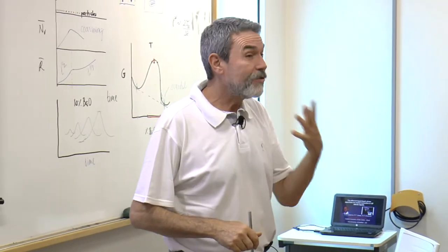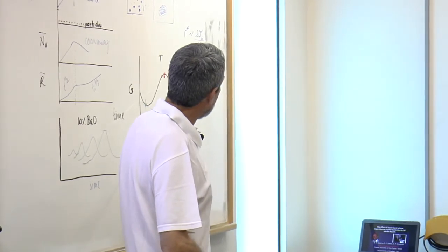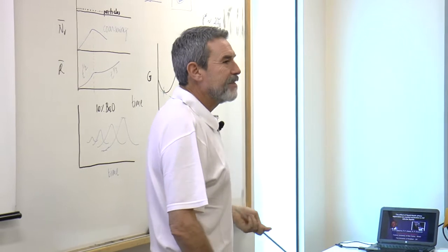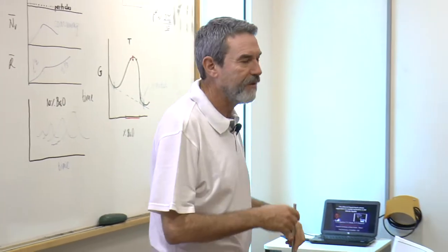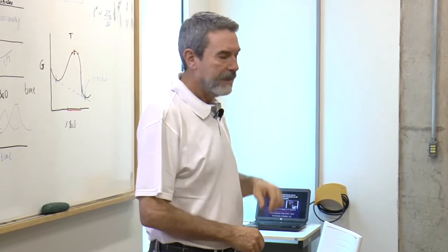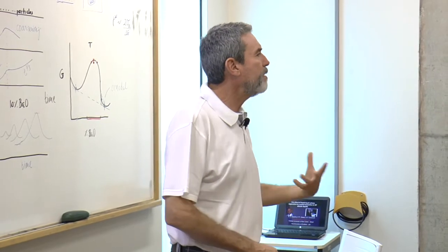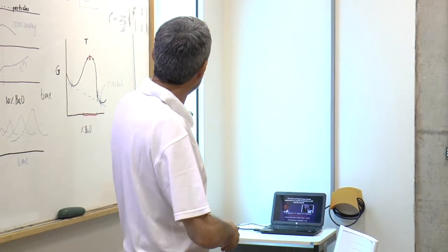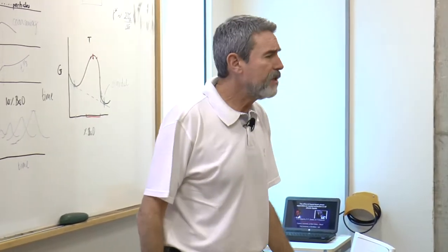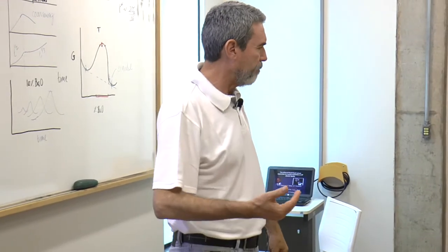Actually, this is extremely difficult because we can calculate delta G well, but the liquid surface energy is a very difficult quantity to get. We can only estimate the liquid surface energy. But with reasonable estimates, you can have an idea, and if you do this, you see there's a few angstroms. For crystal nucleation, I have a much better idea because I have worked so much more.